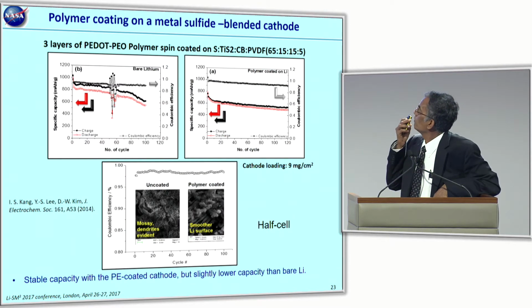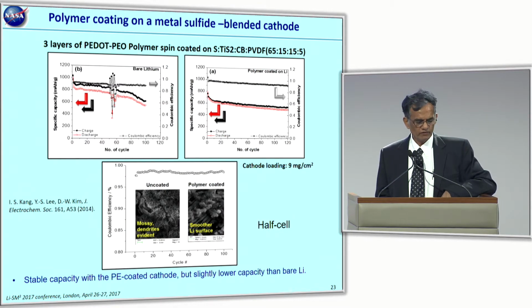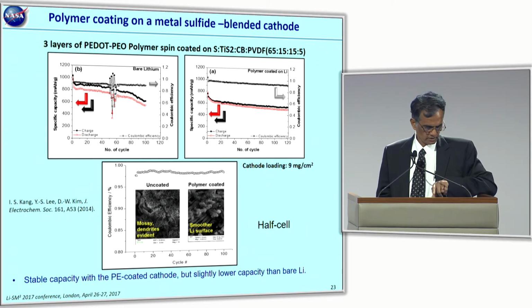And moving on, we also looked briefly at a polymer protected lithium anode. Here we looked at a PEDOT-PEO type polymer, which is spin coated onto the lithium anode. On the top left, without any such coating, with bare lithium, you can see the onset of lithium dendrites around 50 cycles. You can see the voltage capacity is going all over because of the dendrite formation.